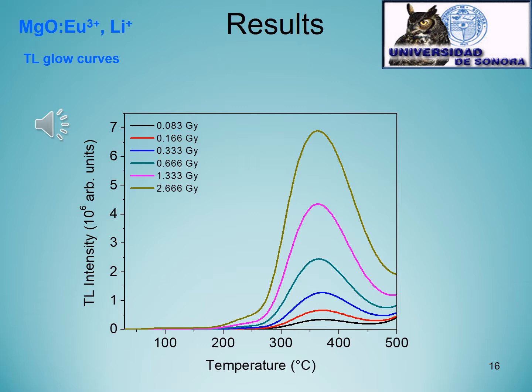This material is obtained by a glycine-based solution combustion synthesis. So we can observe a TL glow curve with a very intense maximum or peak located at around 360 degrees Celsius. We can observe that this interval where the peak is located is a black body radiation interval or incandescence.